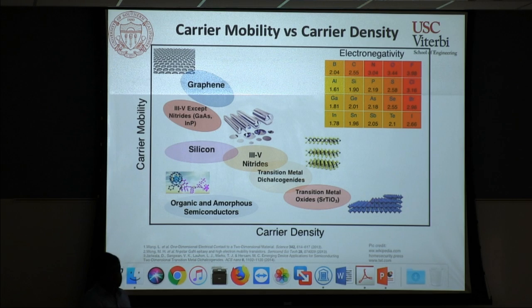in your system. So now, if we can somehow retain this structure and reduce this electronegativity difference between these two elements, you have a mechanism towards increasing the mobility of your system. One way to do this is by taking this system: oxygen has very high electronegativity, and moving down the periodic table, you go to sulfur and selenium, the electronegativity drops.